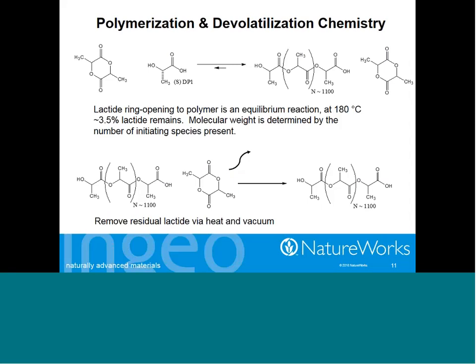The next slide is again just kind of the chemistry update there. We start with a lactide molecule. In this example, I'm showing lactic acid being used as a chain initiator and going to a mixture of residual lactide or equilibrium lactide and polymer. After deactivation of the catalyst, we would then vacuum out the residual lactide or the equilibrium lactide and deliver just the polymer melt. The devolatilization takes place in a vacuum chamber, and the recovered lactide can be recycled back into the process, so that's not a waste stream.